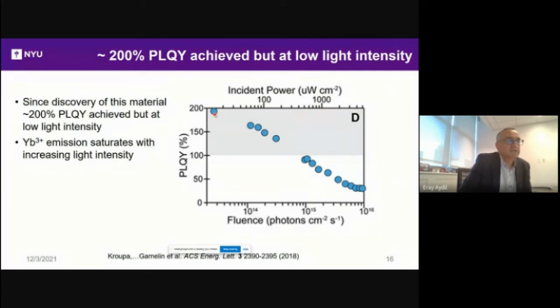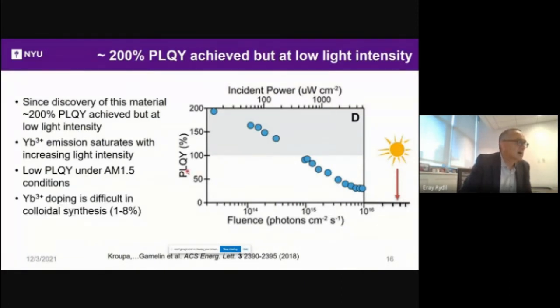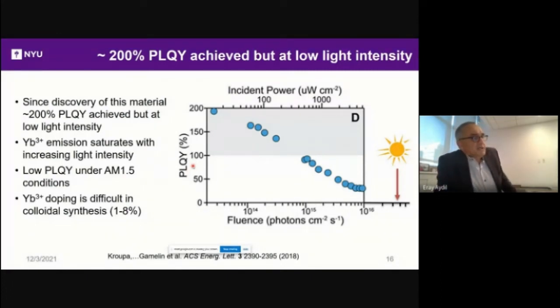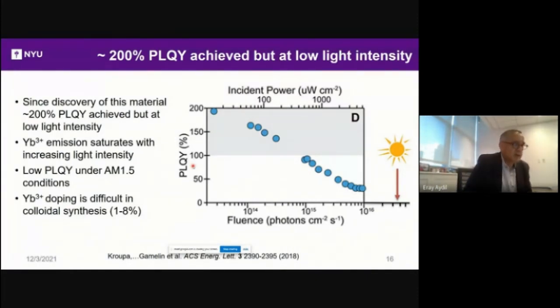However, it saturates with increasing light intensity and the quantum yield decreases. This is a bit of a problem because the sun flux is about there. So it's a low photoluminescence quantum yield under AM 1.5 conditions. I won't talk about how one can remove that, but one of the reasons is that ytterbium 3+ doping is difficult in colloidal synthesis. You can only put 1 to 8% of ytterbium into the material.